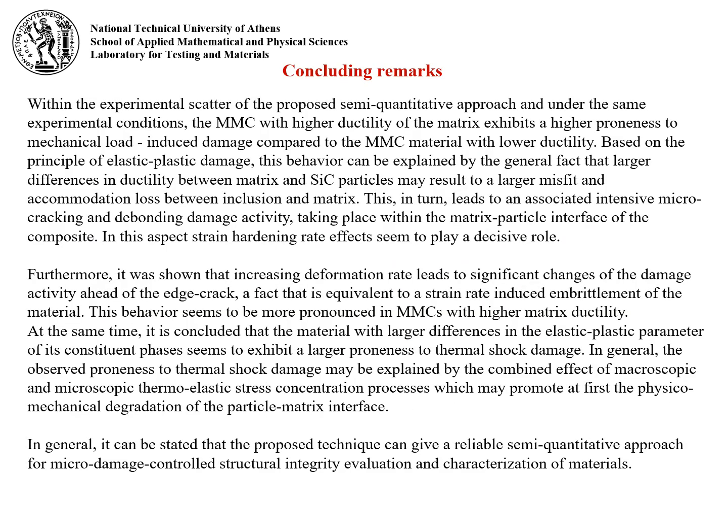In conclusion, the MMC with higher ductility of the matrix exhibits a higher proneness to mechanical load-induced damage. Increasing deformation rate leads to significant changes of the damage activity ahead of the edge crack, a fact that is equivalent to a strain rate-induced embrittlement. This is more pronounced in MMCs with higher matrix ductility.